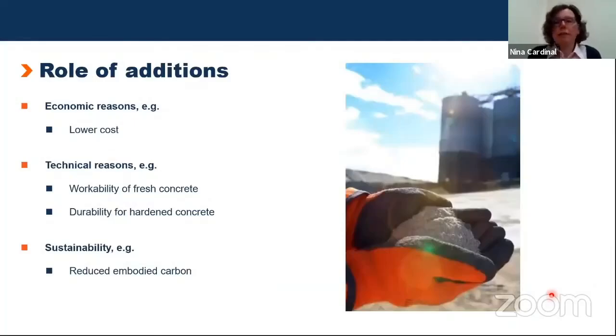What is the role of these in addition to Portland cement? Initially, they were introduced for economic reasons because fly ash and GGBS were cheaper than Portland cement. But many on this call will also know that they are also needed for technical reasons. For example, silica fume improves the pumpability of concrete, and of course durability, like resistance to carbonation or chloride ingress, is much improved by the use of GGBS and fly ash. And now increasingly, there is a demand for these additions because they have a much lower embodied carbon than Portland cement.